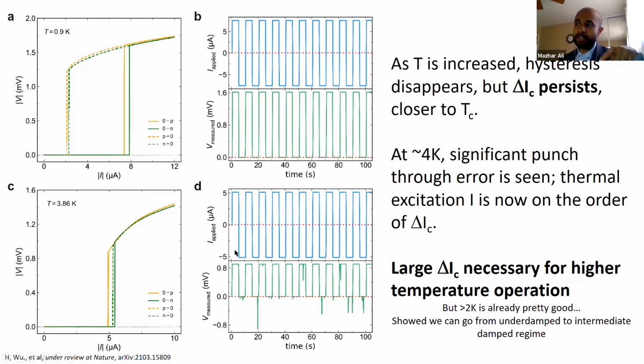So I showed this one here. I didn't actually show the lower temperature. Basically, it's only as we approach like 4 Kelvin that we start to see punch through there. And at very low temperatures, we absolutely don't. So at the 2 Kelvin regime, I think this thing is still going to be very stable. It's still like 3 or 4 times below the TC. And of course, just for stress testing purposes, if we test this in a dilution fridge at 20 millikelvin, who knows? Let's see what happens.